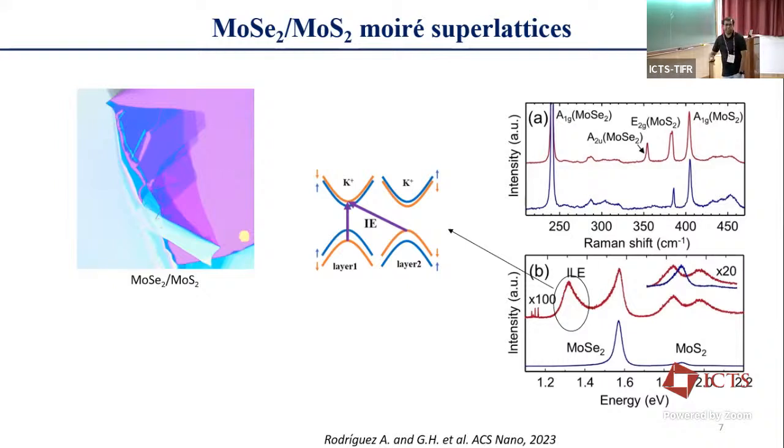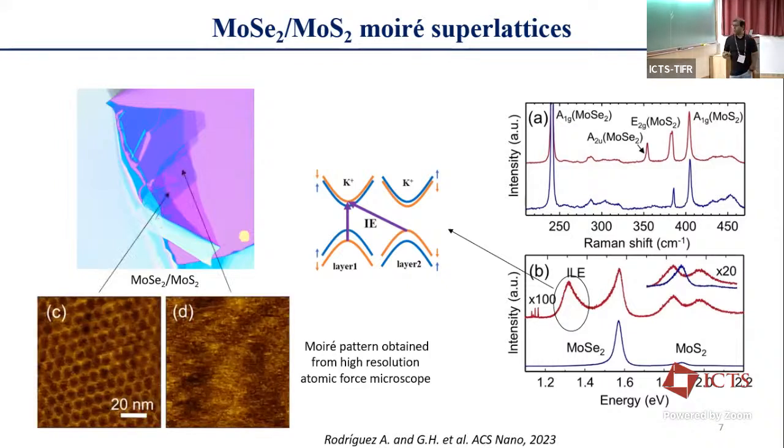So all those things are really nice. We can now characterize whether the two layers are talking to each other or not. By probing this new mode, we can understand that the two layers are interacting. Also, there is another signature that these two layers are interacting. Now, if we measure, let's say, conducting AFM in this kind of heterostructure, we see that the Moire patterns appear in this region. But if we measure AFM there, clearly there is no sign of the appearance of the Moire pattern.